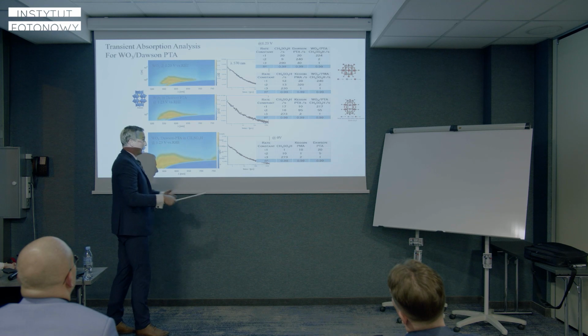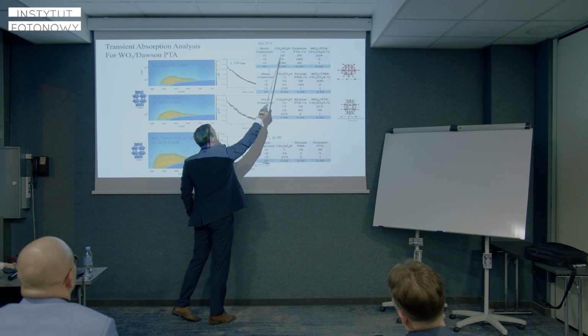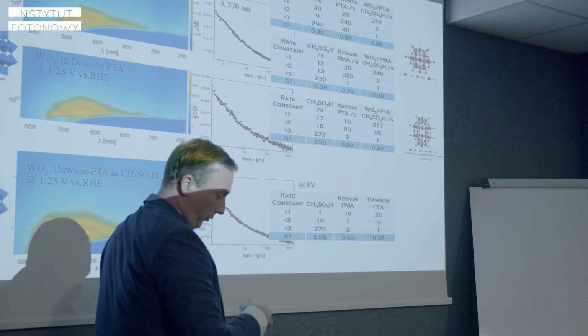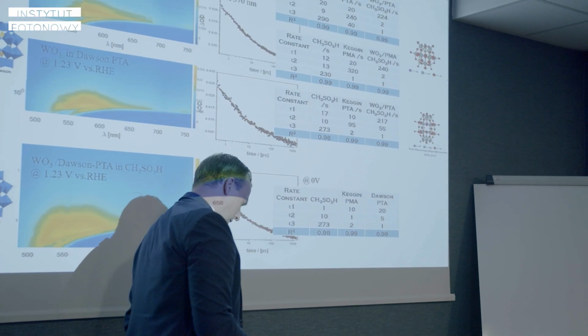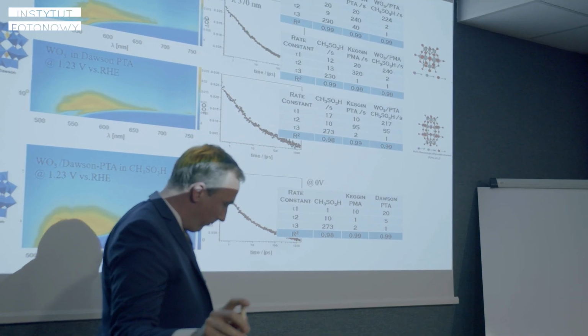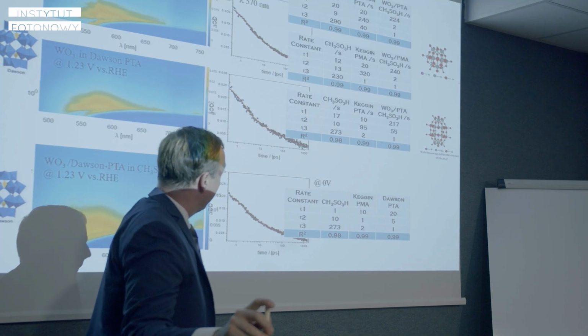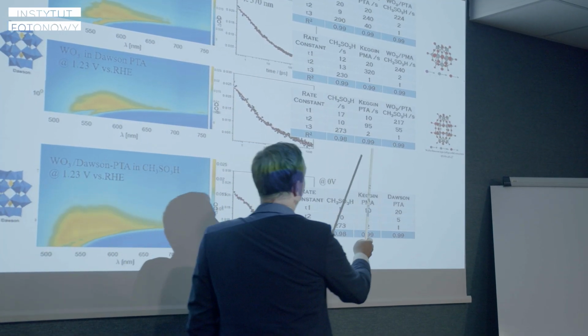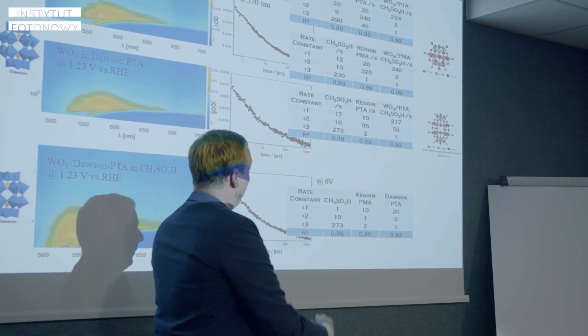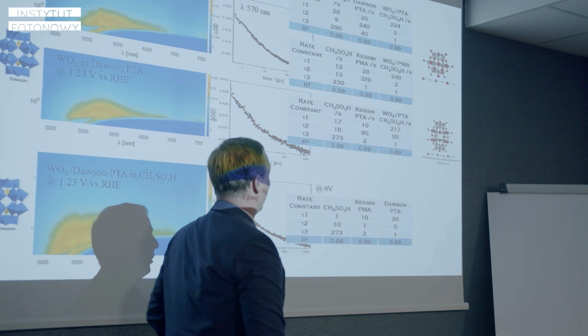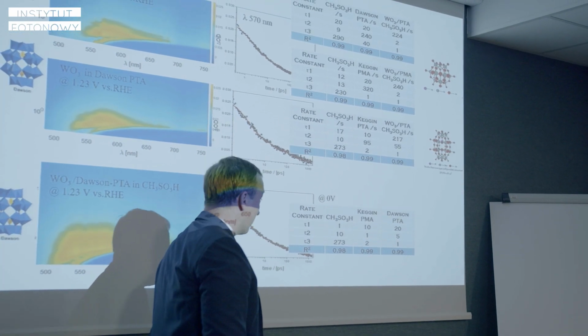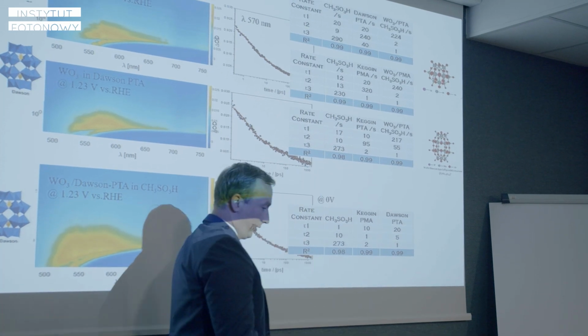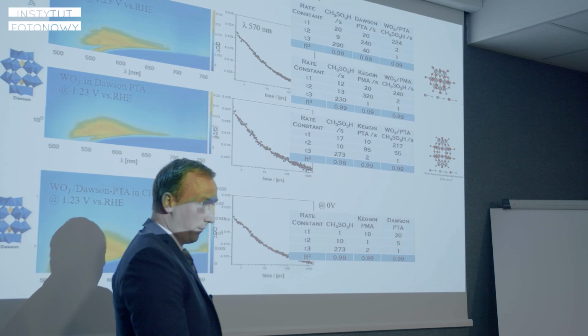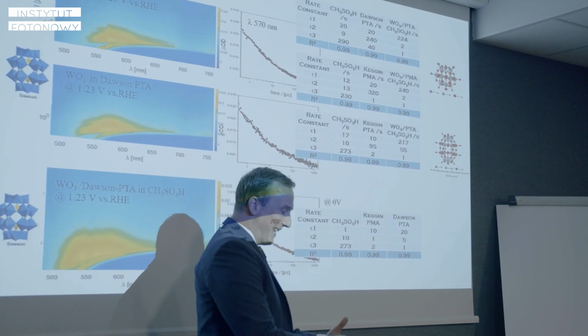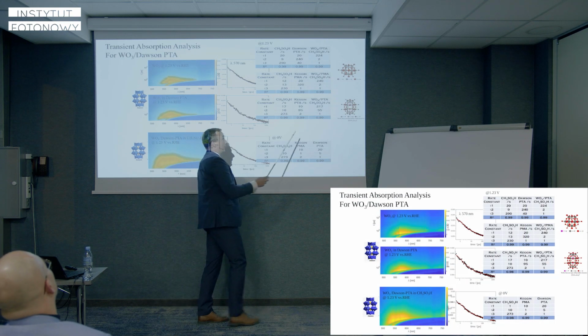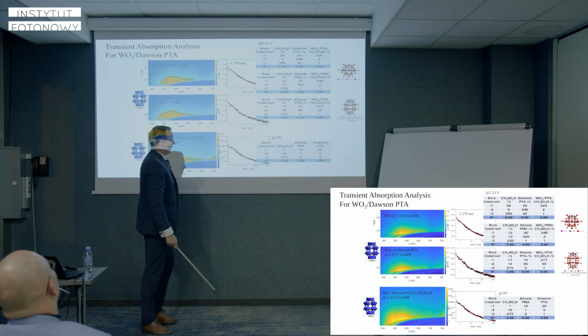So how does our experiment look? We measured the time decay for our materials in pure acid, this is methanesulfonic acid. And secondly, we put polyoxometalate inside the solution. We measured the time decay of the created holes, and after this we took off the electrode, washed it with acid, put this electrode into the electrolyte one more time, and measured the decays again.